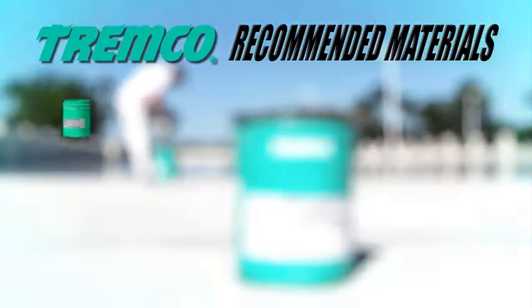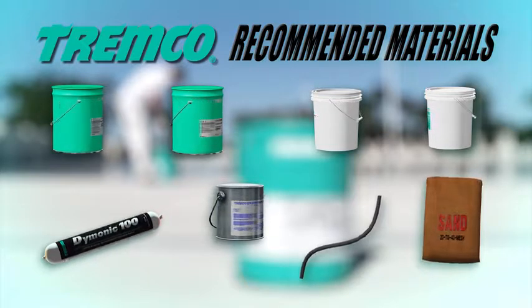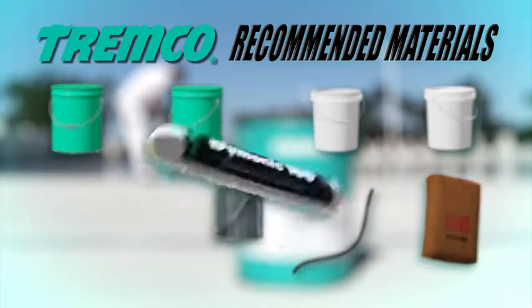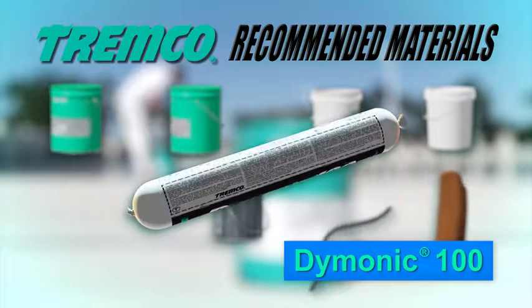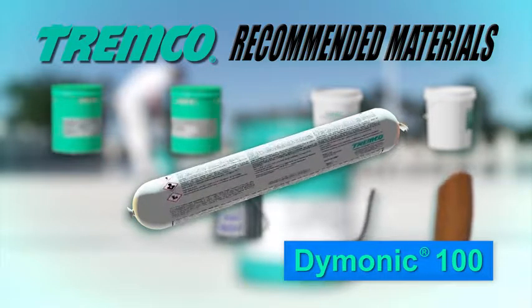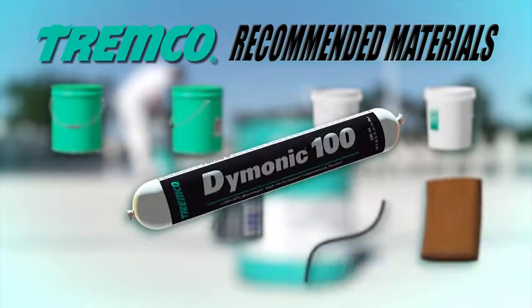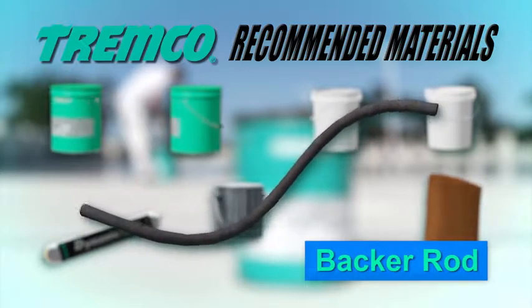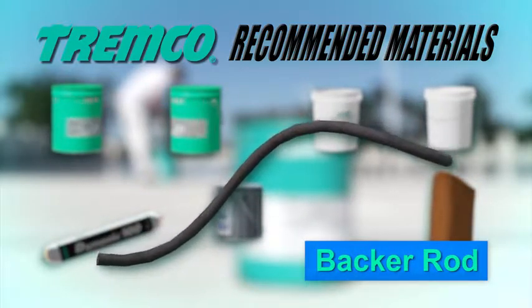The following products are recommended for use with the Vulkem 350NF 346 deck coating system. Dymonic 100 is a one-part moisture-curing gun-grade polyurethane sealant used for sealing cracks, control joints, drain detailing, and for use in forming cants. A closed-cell polyethylene backup material should be used in control joints and at the base of cants to prevent three-sided adhesion and to control the depth of the sealant.